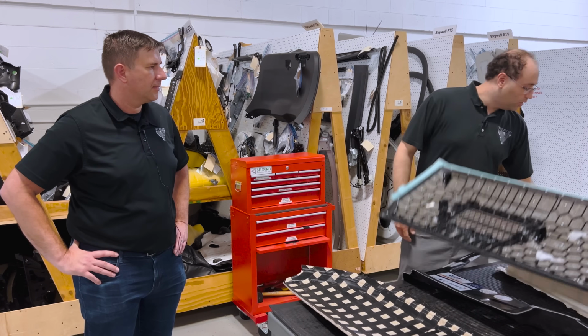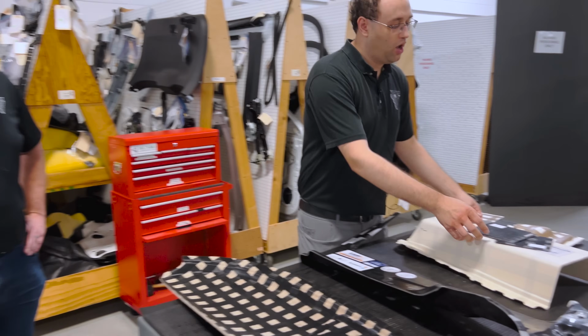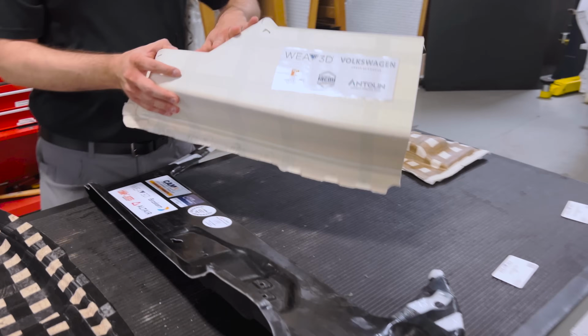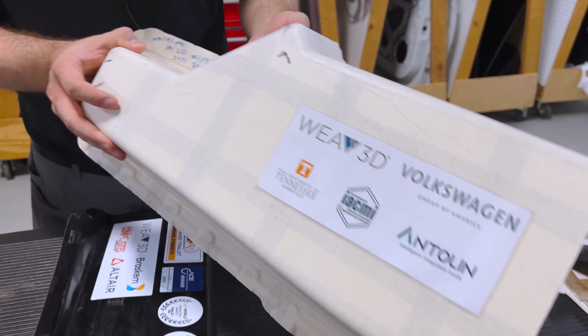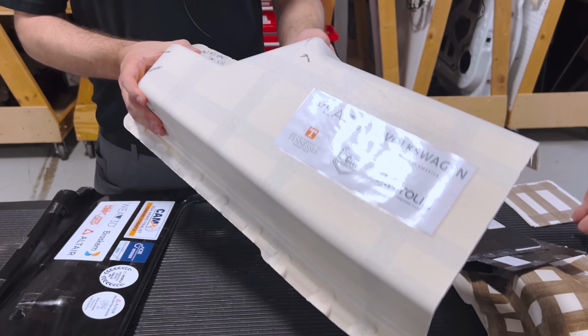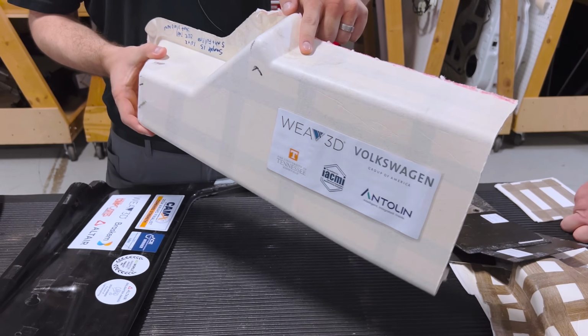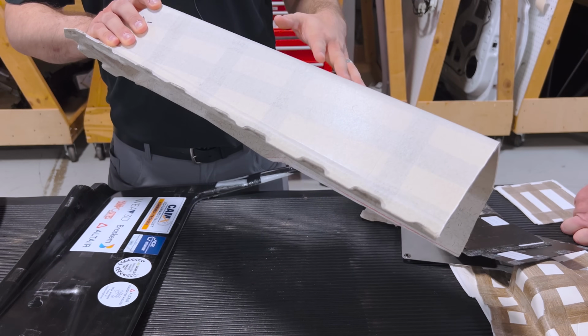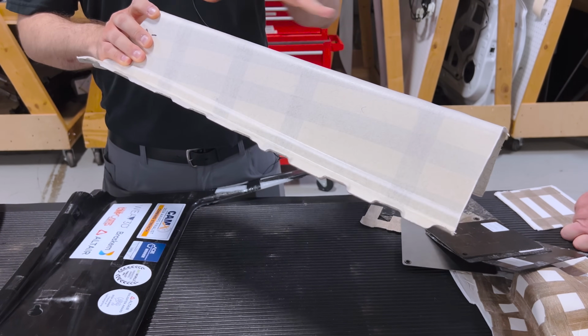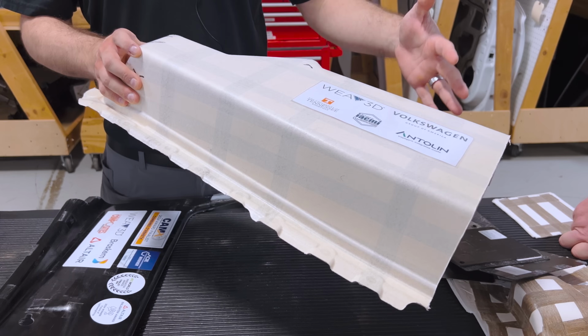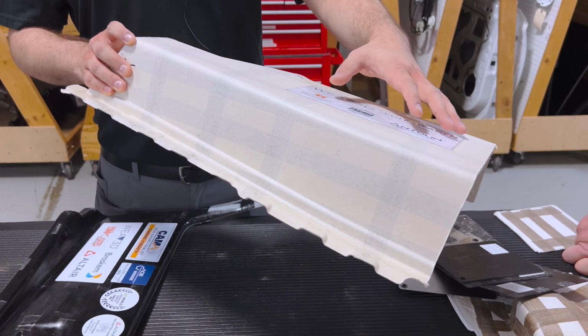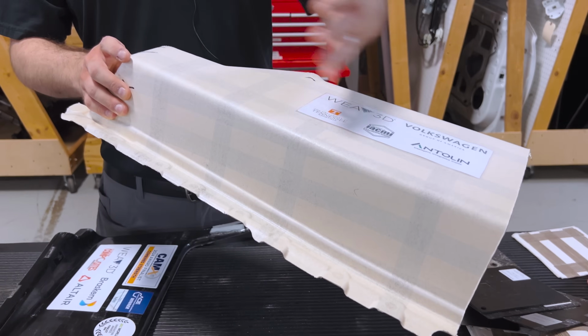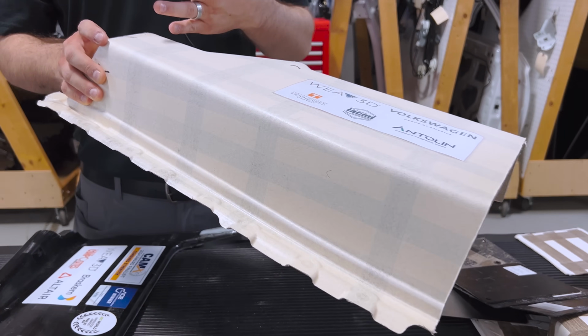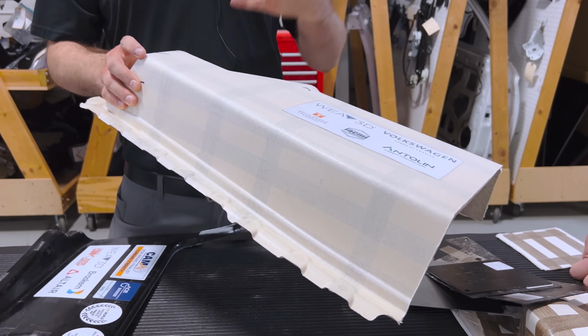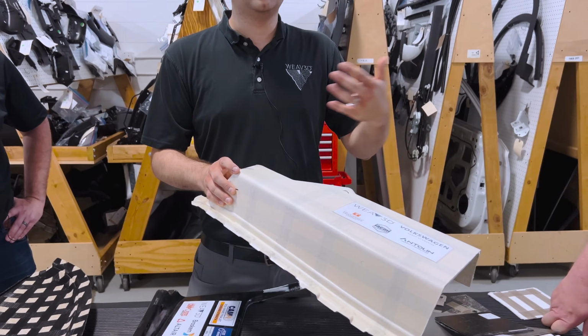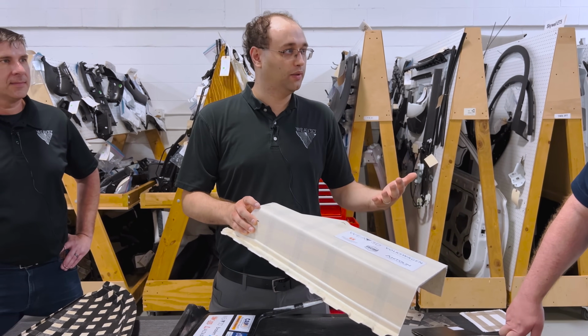I can give you an example over here of a non-homogeneous design. So this is not NFPP, it's actually a cellulose non-woven material that was developed by Volkswagen. But you can see there's a lattice in this part, and that lattice has an uneven distribution within the structure. So in this particular case, we're both reinforcing this material so it's easier to form, but we're also providing additional stiffness in this part by tailoring it where it needs to go in the part for performance purposes. So that means I can use less of the continuous material and still get the performance that we're aiming for in the finished component.